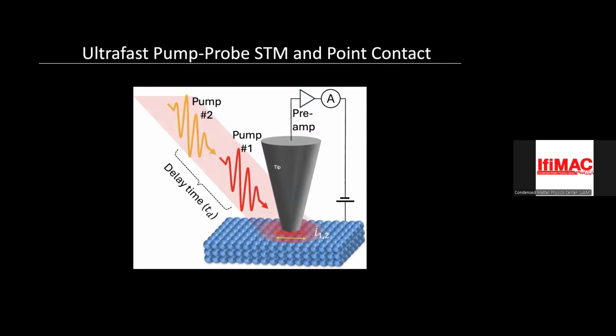Pushing hard. Yeah, exactly. We just slowly bring the tip closer, and we know when we are touching. Beyond that, we push a little harder. We have done distance-dependent measurements, and if you go too deep, then you start losing the signal. It's probably creating pressure. Our signal strength depends initially on how hard we push, and then we start losing our signal. I can tell you that we're extending the tip, but how deep it's going is a completely different story. When we image again, depending on how much we push, we can see the little damaged area. It's not very big, it's nanometers. So it's a pretty nice little point contact, and it's really not damaging large areas.